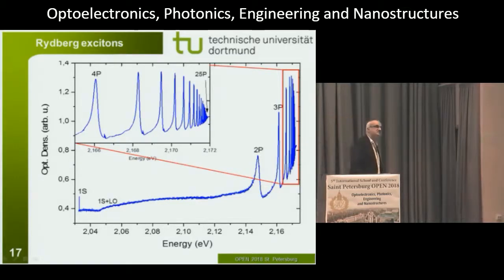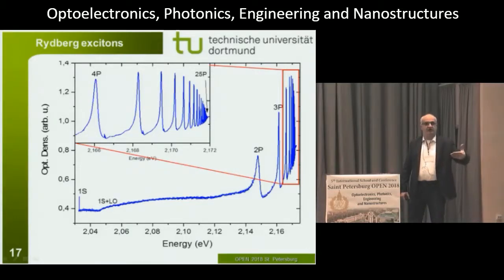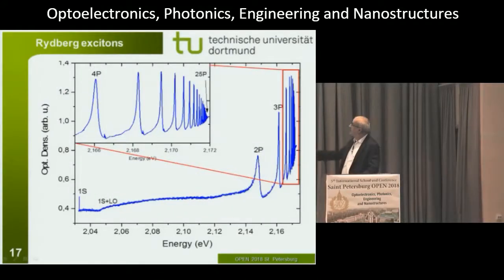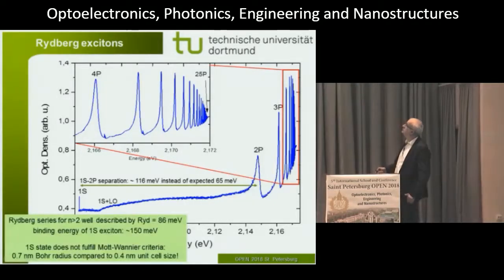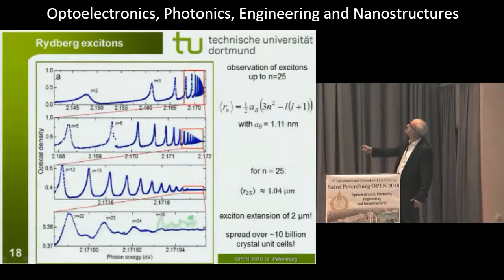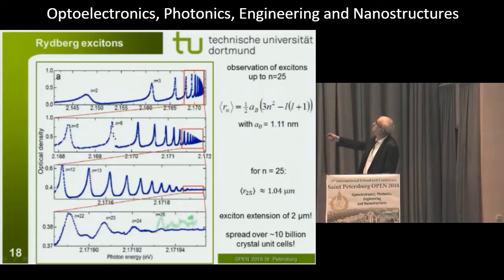I told you that this is dipole forbidden. That's true, but it is quadrupole allowed, so in next higher order, and this is why we can observe it with these fancy laser systems. Then we scan to higher energies, roughly 1 LO phonon above the 1s exciton. Phonon-induced or assisted absorption starts. This is not important for this case. Then at some point we find the 2p exciton and then the 3p exciton, and I won't go into too many details here. If we then zoom in into the series, we find here n equals 2, 3, 4.